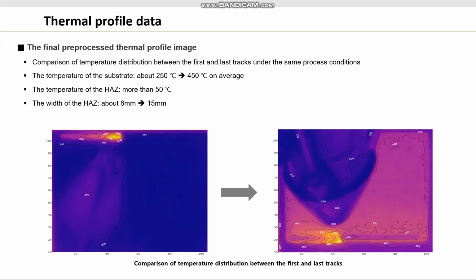Okay, you can see the final preprocessed thermal profile image in this slide. The picture on the left side shows the temperature distribution when the first bead was clad, and the picture on the right side shows the temperature distribution when the last bead was clad. As the laser cladding proceeded from the first bead to the last bead, the temperature distribution of the substrate changed. Even under the same process conditions, the temperature distribution of the substrate increased from about 250 Celsius degrees to 450 Celsius degrees on average.